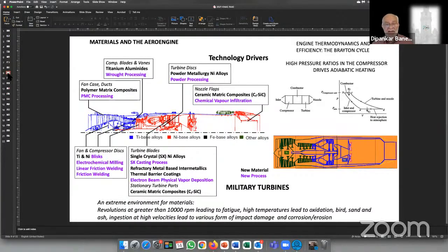The aero engine environment is, of course, an extreme environment for materials. So revolutions greater than 10,000 RPM lead to fatigue. High temperatures lead to oxidation. Bird, sand, and ash ingestion at high velocities lead to various forms of impact damage, corrosion, and erosion.